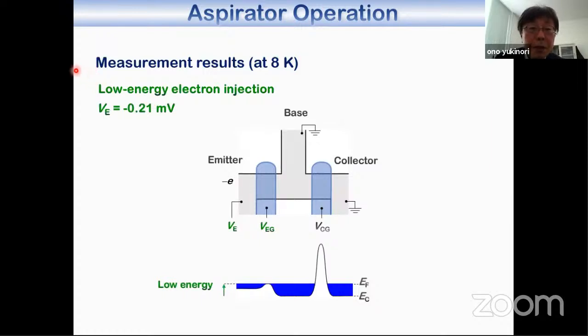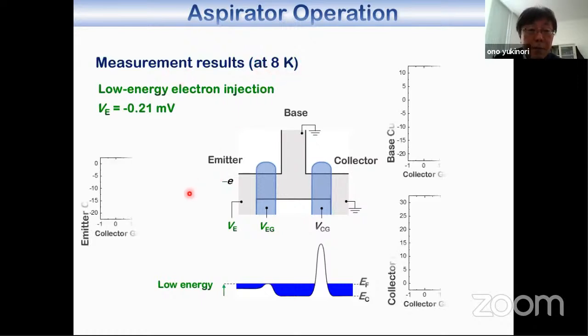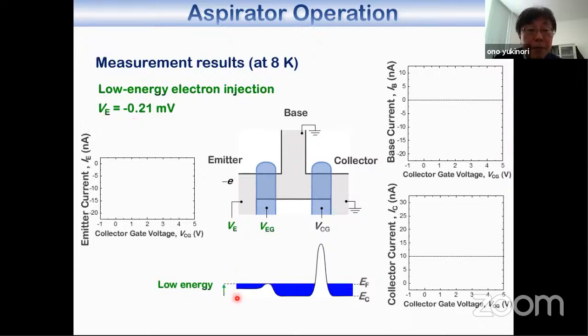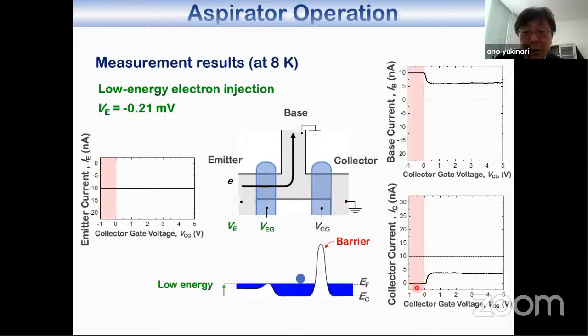So let me show you some measurement results. Those measurements were done at 8 Kelvin. First, I'd like to show you what happens if this energy is very small. These are the data of emitter current, base current, and collector current as a function of the collector gate voltage, which is this. As I explained, the emitter current was kept constant at 10 nanoamps. Then, when the collector gate voltage is below the threshold, we have the large barrier here, so that all the electrons go to the base. Therefore, the base current reaches 10 nanoamps, which is the same as the emitter current, and the collector current is 0.